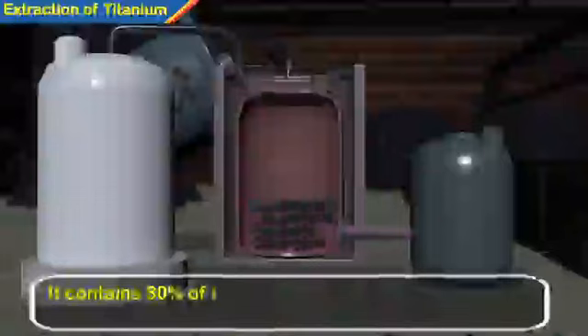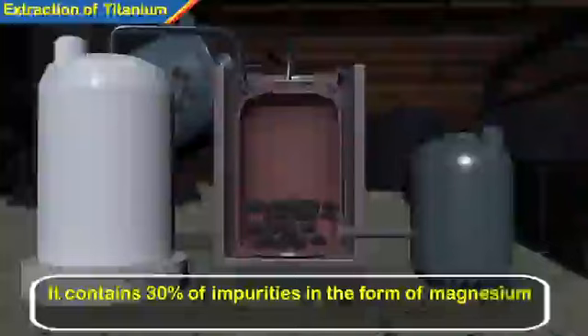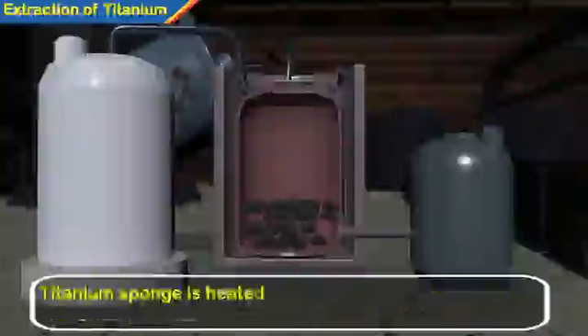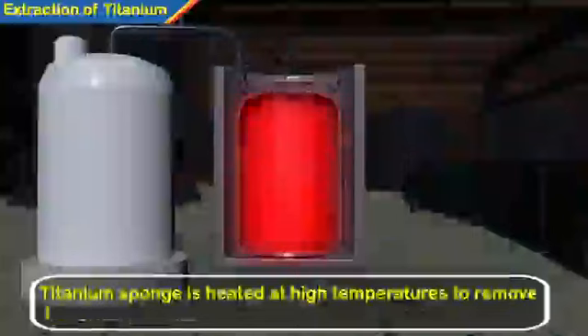It contains 30% impurities in the form of magnesium chloride, that is MgCl2. Titanium sponge is heated at high temperature to remove impurities from it. Later, titanium sponge is melted in the presence of argon to produce pure titanium slabs. Similarly, titanium can be extracted by using sodium as a reducing agent at about 1000 degrees Celsius instead of magnesium. In this reaction, sodium replaces chlorine and forms titanium and sodium chloride.